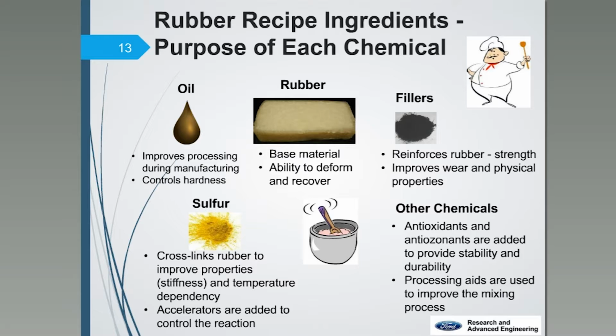Sulfur is also used. That's helping to cross-link the rubber to improve the stiffness, as well as the temperature range of operation. You might have heard of vulcanization, and that's what's happening with the sulfur and the accelerators. It's providing cross-links between the polymer chains, allowing the material to deform and come back to its original shape. If you think about just regular rubber that hasn't been vulcanized, if it gets too hot, it gets very sticky. If it gets too cold, it becomes a hard ball, or kind of glassy, I should say. And vulcanization broadens the temperature range of operation so that maybe it doesn't get sticky until a much higher temperature, and it doesn't get glassy until a much lower temperature.